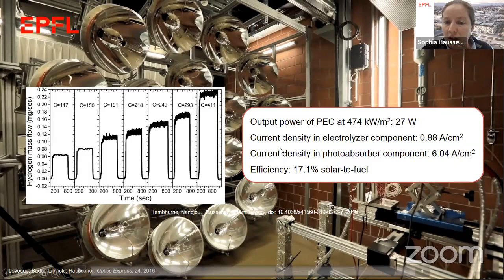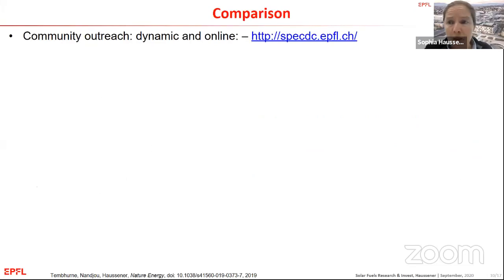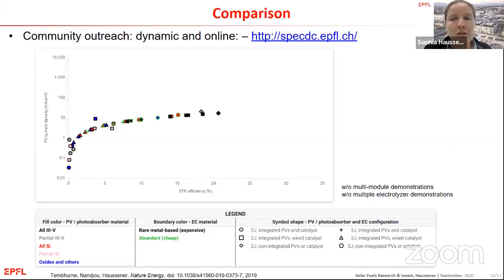Basically, I want to highlight this efficiency. It's not a peak efficiency that has been demonstrated, but for the high current density where you have to deal with so much larger losses than in low current density devices, it's actually quite an achievement. But let me convince you by just looking at all the different demonstrations that have been done in the field. You can see each data point is some university or research institute that has demonstrated hydrogen production. You can see that the colors and the shapes of these demonstration points are different, which are taking into account that different materials, different designs are used. So we're comparing apples and bananas a little bit, but nevertheless, it gives us an idea of the trends.